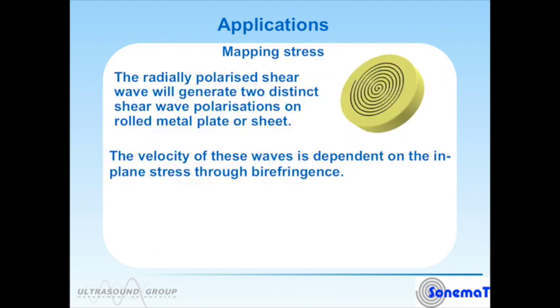We can use this same kind of EMAT to map stress. In a metal plate that's been rolled or cold worked, there are generally slight levels of anisotropy. Anisotropy equates to different elastic properties in different directions. They're very small, but they can have a significant effect on ultrasonic propagation. In this case, if we send a shear wave down through the thickness direction of the sample, that shear wave will split into two polarizations. One is a shear wave that vibrates along the rolling direction of the plate. Another vibrates at 90 degrees. And by looking at the relative velocities of these two waves, we can actually map stress.